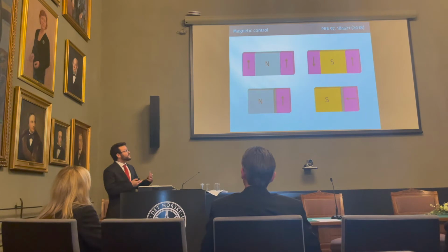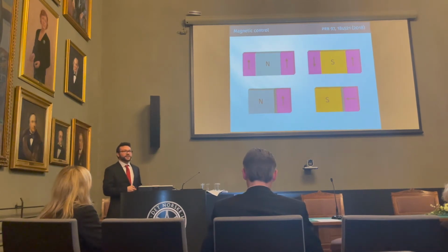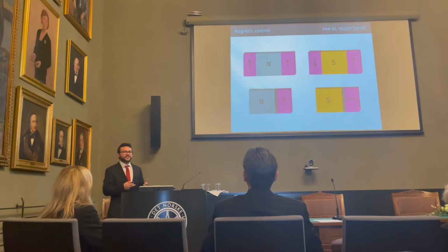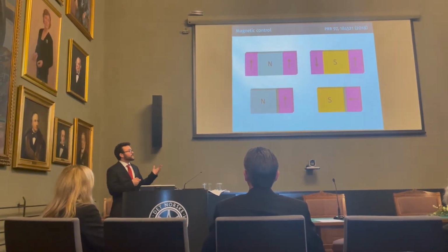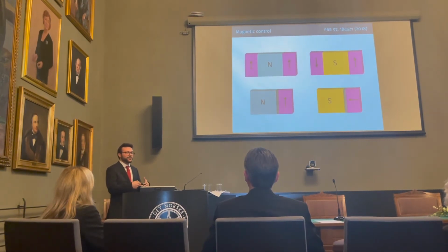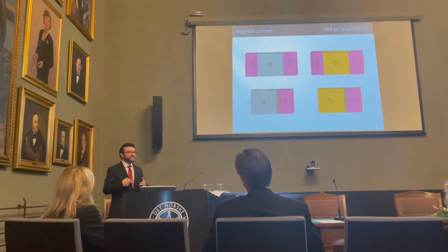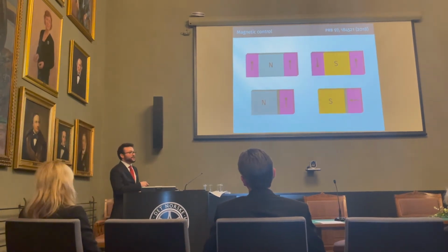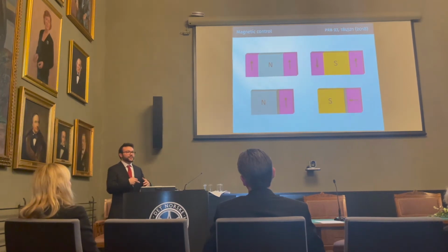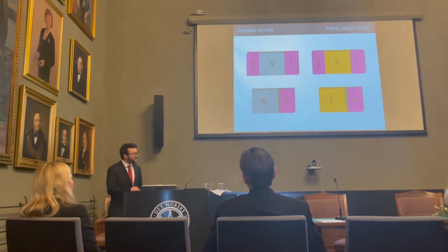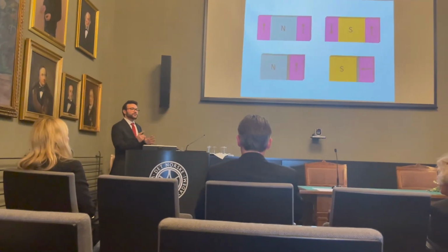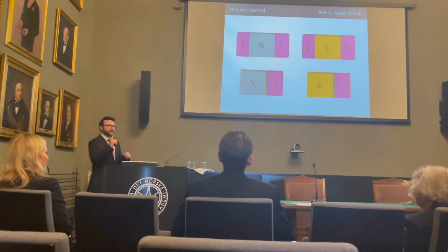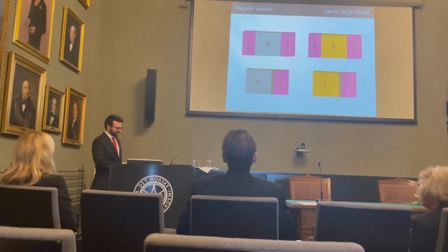And I don't have time to go into full detail on how this works, but the short summary is that it's related to a relativistic effect known as spin-orbit coupling, which in this case causes some forms of superconductivity to be destroyed by the spin-orbit coupling, while other types of superconductivity are not. And then which direction the ferromagnet is pointing is then related to which types of superconductivity exist in this structure. But to summarize, this is then a new way, and hopefully a simpler way, to control superconductivity using magnetism that only requires you to control one magnet instead of two.